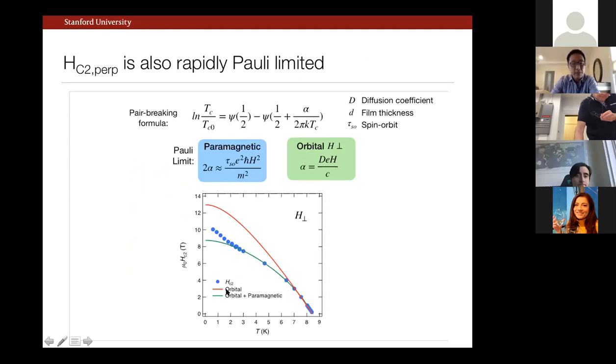And so, for example, if we take a simple fit to just an orbitally limited upper critical field, we would have this red curve. But if we take this consideration of pair breaking by spin-orbit scattering into account, we would get this green curve. And the point of this, qualitatively, is to say that even fairly close to TC, we rapidly cross over to be limited by the paramagnetic response as well.